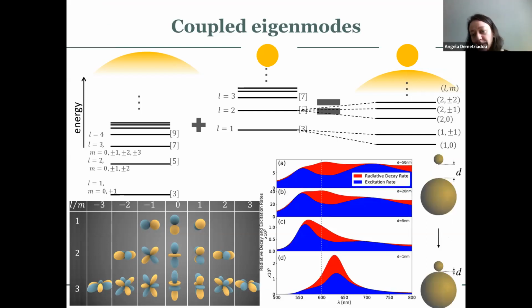And now if I want to see what's happening to the excitation and radiative decay rate in this system, I start by plotting both quantities for the small and the very large nanoparticle when they're separated, when they have a very large separation, in this case 50 nanometers. With 50 nanometers, it means they're not really interacting with each other. And because the larger nanoparticle gives you a stronger behavior, the only thing that I'm seeing basically in this figure is the behavior coming directly from the very large nanoparticle. So I see the difference between the radiative decay rate in red and the excitation rate in blue. I see the differences because of the even modes not being excited for the excitation rate. This dashed line shows where this mode here is for the small nanoparticle.